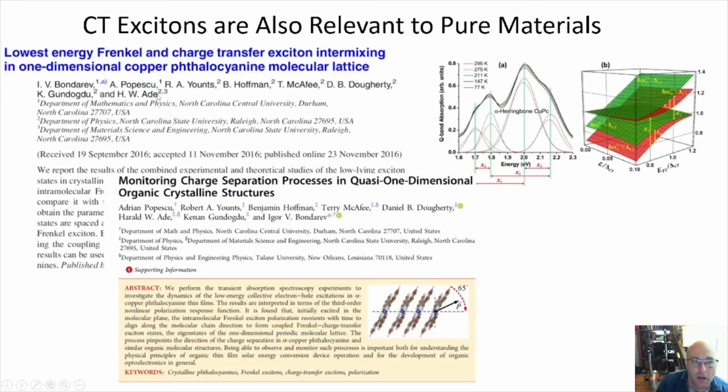Anyway, these 2 guys did calculations to try to produce our optical absorption spectroscopy on an organic semiconductor called copper phthalocyanine. And they found that in order to produce the fine structure associated with these optical absorption spectra, they needed to include substantial CT, LE hybridization effects, that you can't just assume that these are S1 excitons created on the molecule.